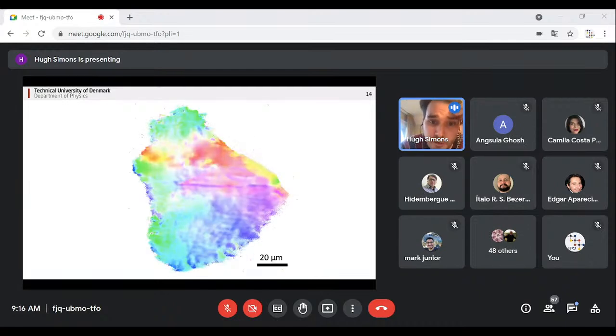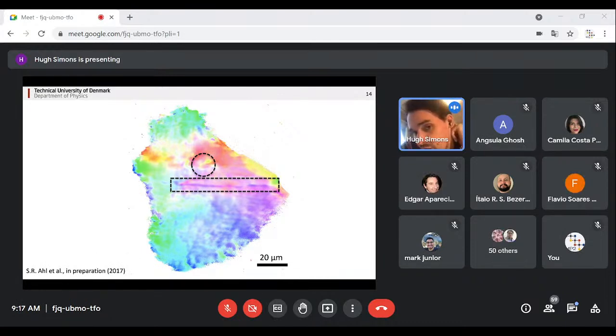And in fact, this is another example of Sonia's work, which showed a line much more clearly. So you can see these lines here and these sharp changes in intensity. These are essentially from very, very low angle grain boundary lines, which are almost single dislocations. In fact, I think the circled area above is a single dislocation. And so we got to thinking, if we found the right sample and we improved the resolution a little bit, is it possible that we could see individual dislocations buried deep inside millimeter samples? And that's the size of the samples we're working with here, they're about 1 millimeter thick.